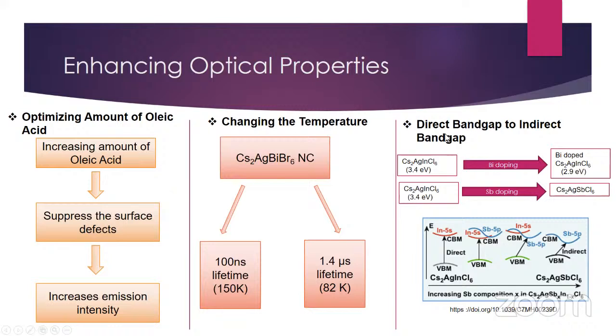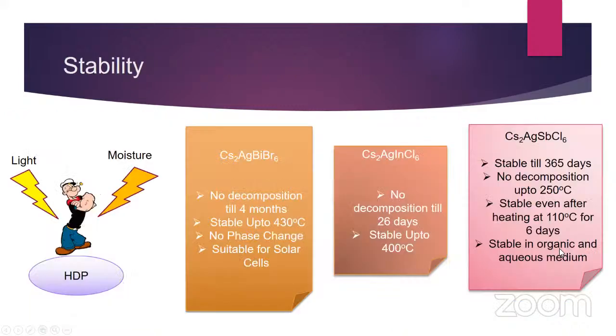And there is also one very interesting change, like you can change the material's direct band gap to an indirect band gap. Here you can see we have started with Cs2AgInCl6, then we have done this bismuth and antimony doping, and as a result we are getting an indirect band gap. So if you see in this diagram, at first the band gap was high and it was a direct band gap, and when you are increasing the amount of antimony, then it is becoming an indirect band gap, and also the band gap is decreasing here.